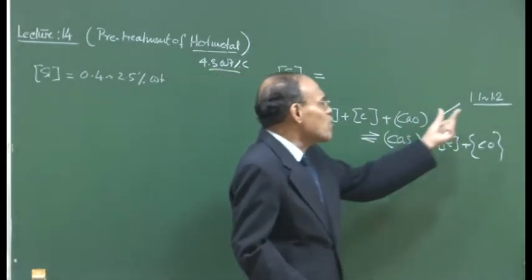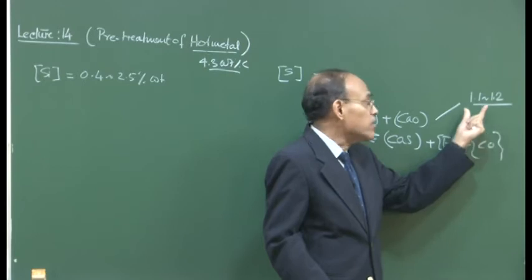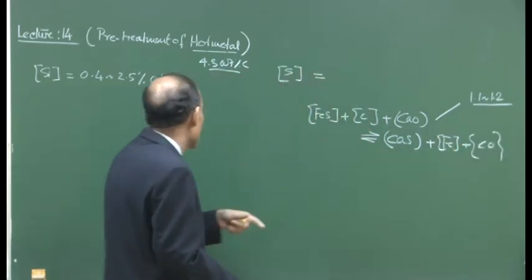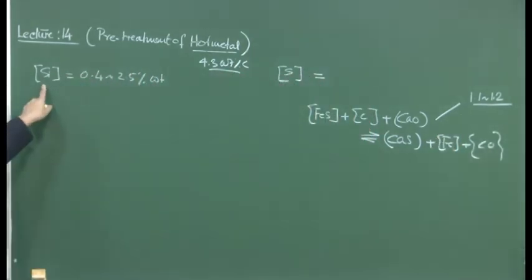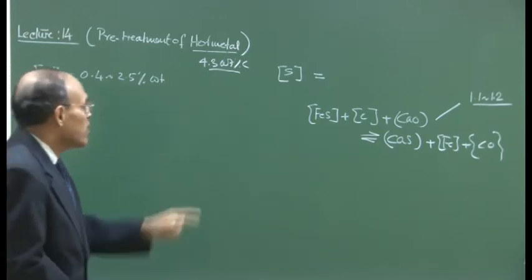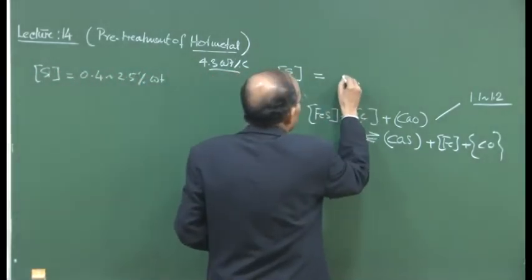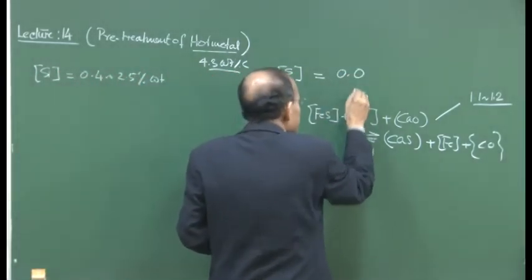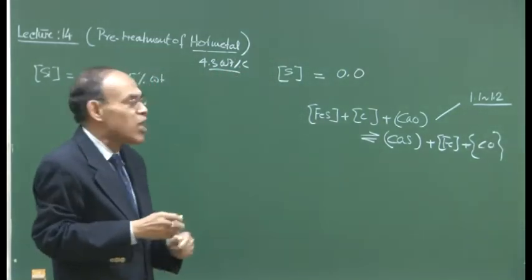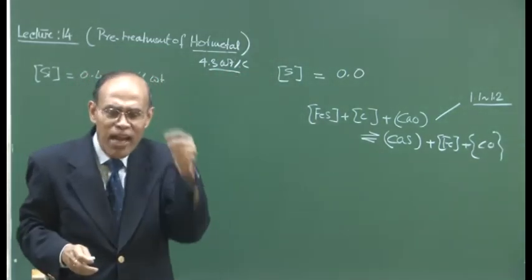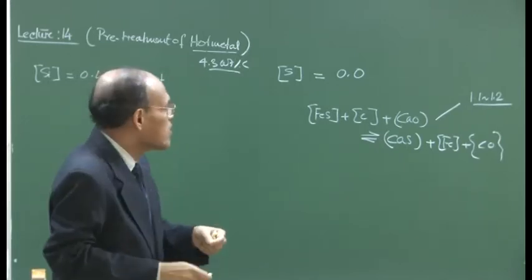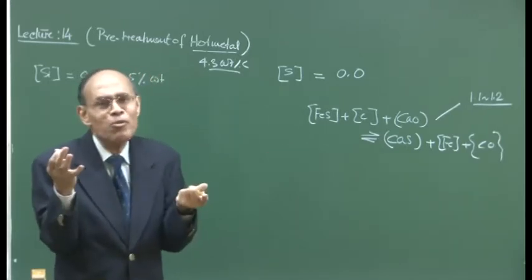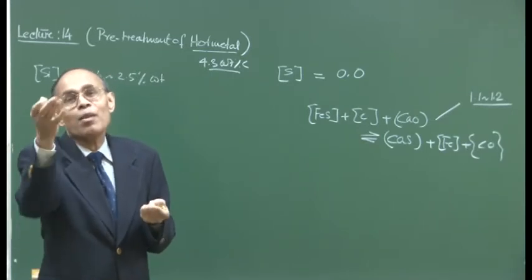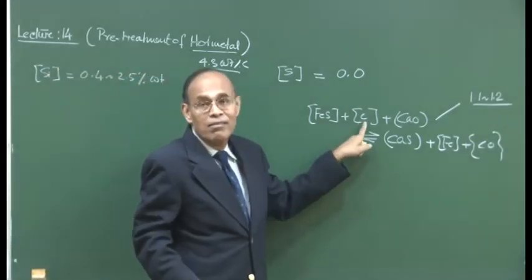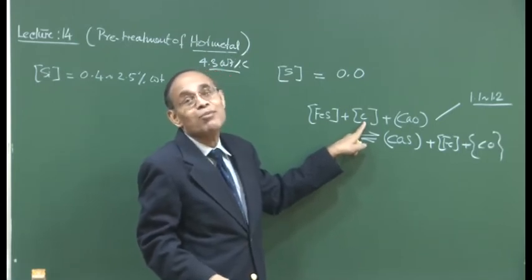So you are constrained to limit the basicity, because you do not want to go to high temperature. If you go to high temperature, then the silicon content of the hot metal is going to increase. So there has to be a compromise. It is interesting that blast furnace can remove sulfur, there is no doubt about it. The blast furnace is the site where you should try to eliminate sulfur to the extent possible, because in steel making you will not be able to eliminate sulfur, for the simple fact that one of the basic conditions that you require, a reducing environment, is not satisfied in steel making.